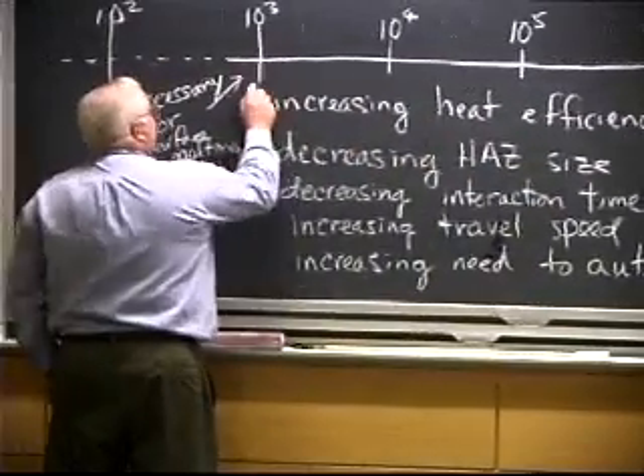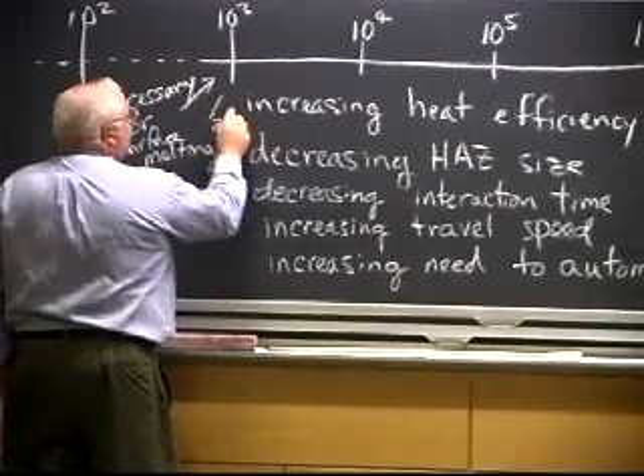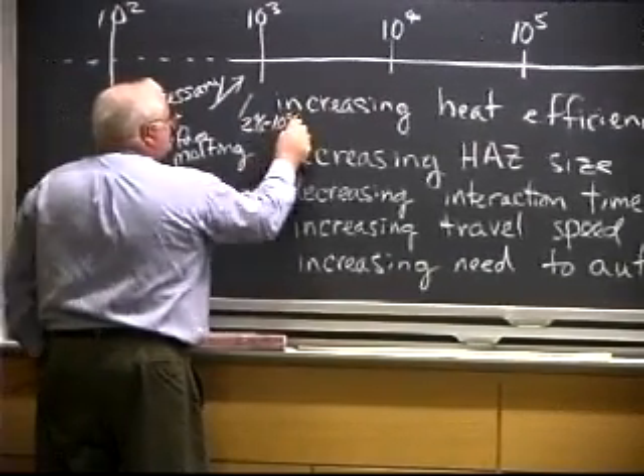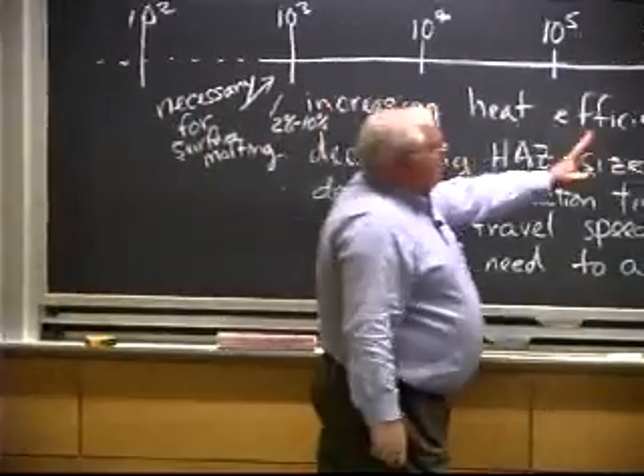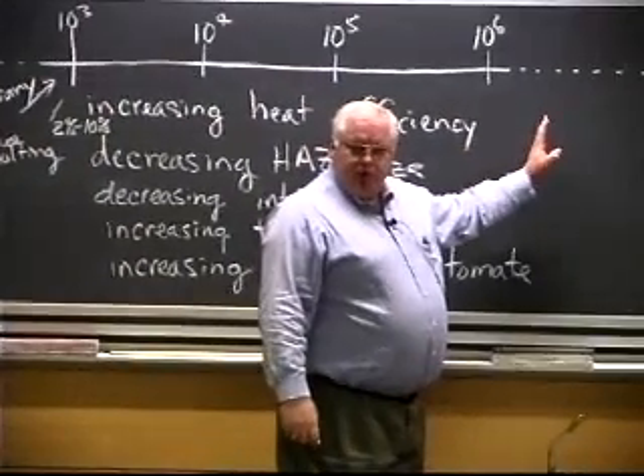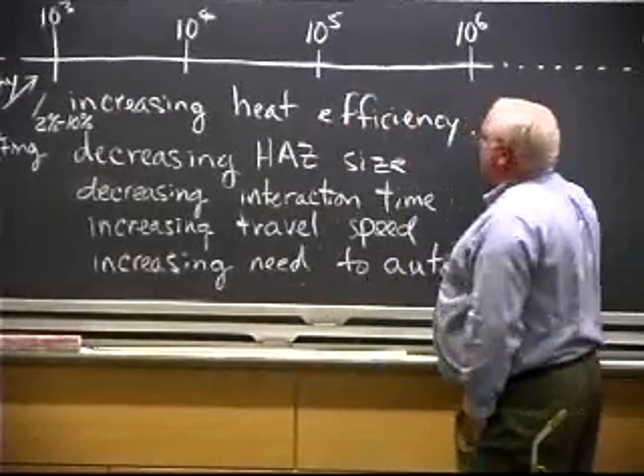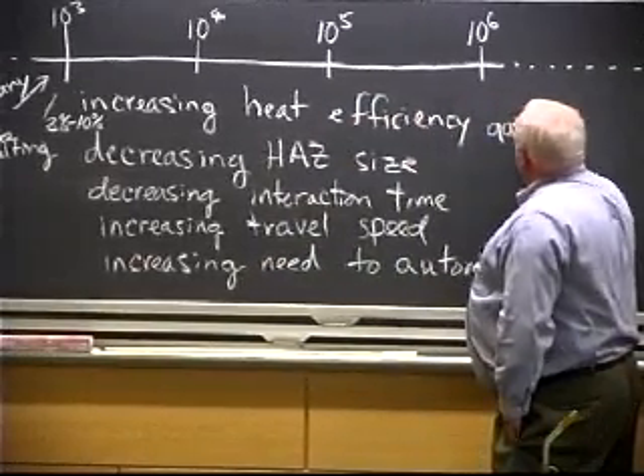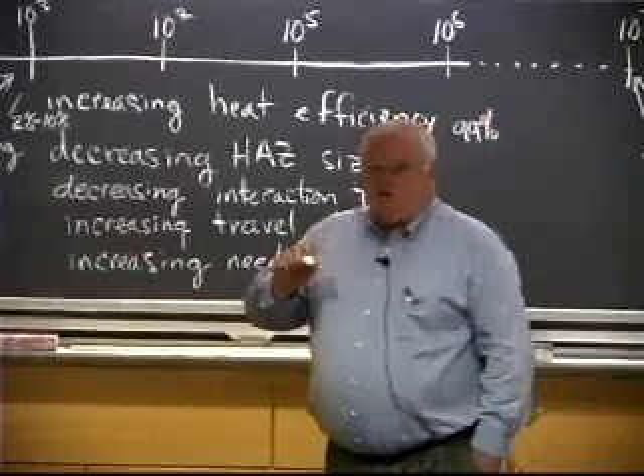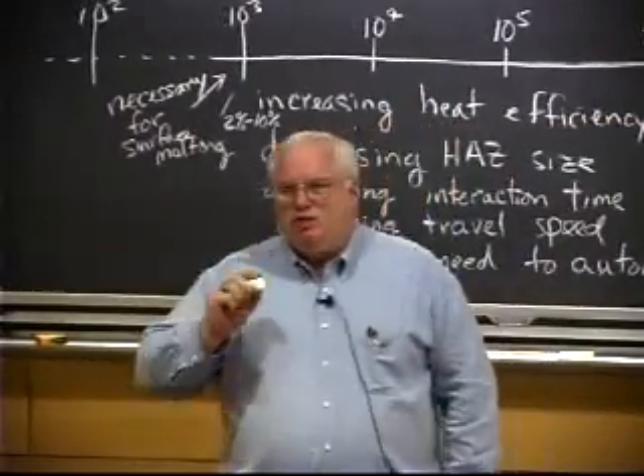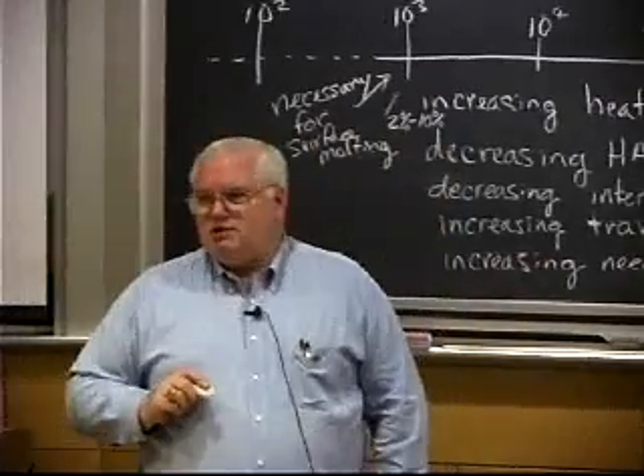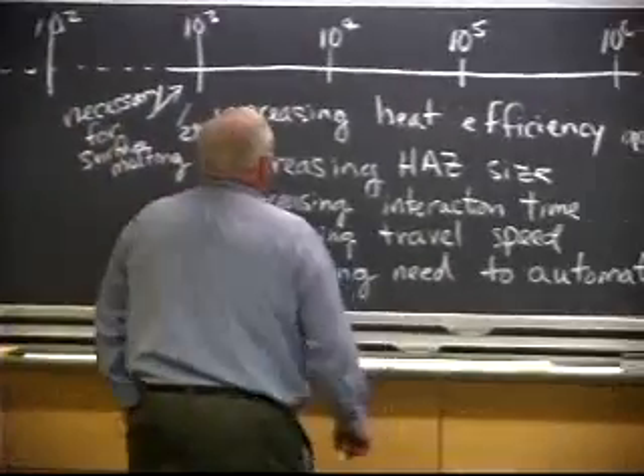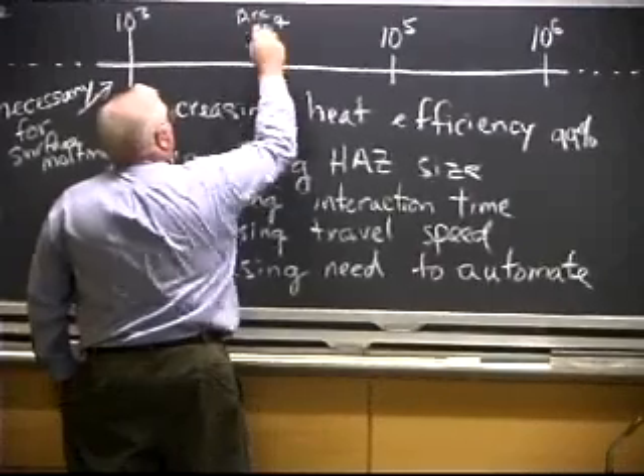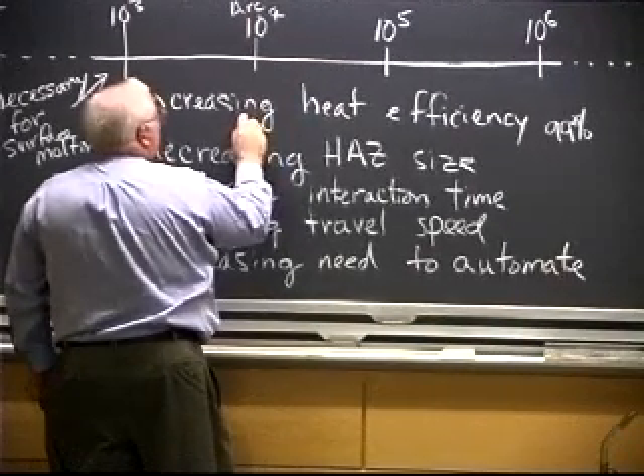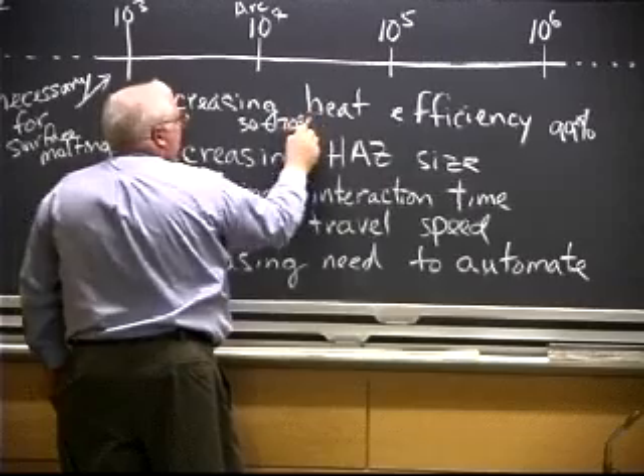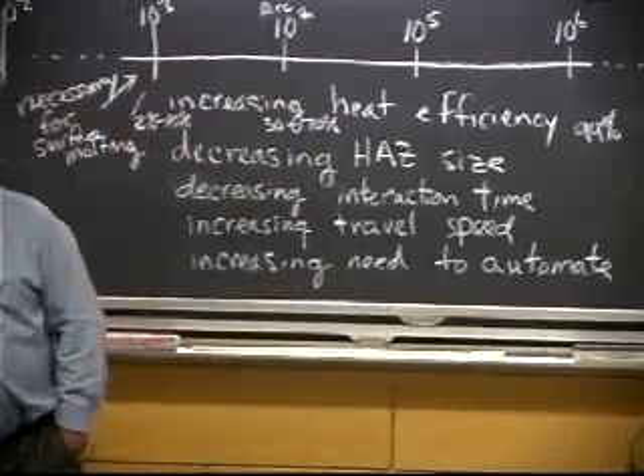And so typical types of efficiencies down here are going to be 2% to maybe 10% in some cases. Whereas over here, you're blasting the material, and if you only go in with 1,000,000 watts per square centimeter, you can make laser and electron beam welds. And in some cases, people have measured 99% heat efficiency. Basically, almost all the heat you put into the thing is going into melting. And whether you believe 99% or whether it's 97%, doesn't matter. It's above 90%. For typical arc welding, which is by far the most common, we're in the 30 to 70% range for heat efficiencies. Not terrible.